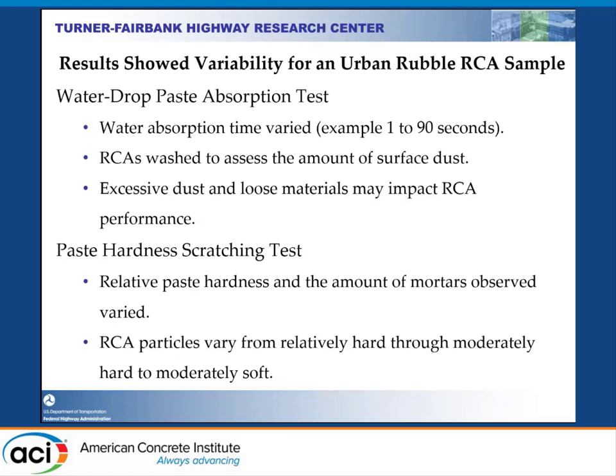Results showed variability for an urban rubble RCA sample. For example, the water drop paste absorption test showed water absorption time varied from one second to 90 seconds — very slow in some cases. I watched this under a stereomicroscope: you drop water and time how long it takes to seep through the paste. RCA was also washed to see the amount of surface dust, since excessive dust and loose material may impact RCA performance. Paste hardness scratch tests showed RCA particles vary from relatively hard through moderately hard to moderately soft.